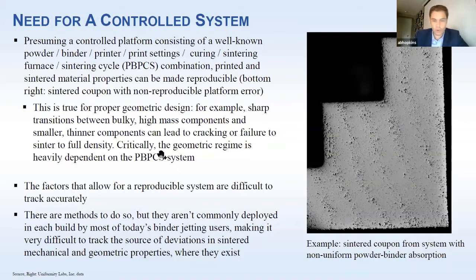All right, great. So once you have a controllable system, you have the problem of geometries again. Is it controllable for all geometries? Or when you sinter, you're going to fracture. So you might see a fracture point at sharp edges in sintering if your part is large enough, even in a controlled system. And it depends on the alloy, it depends on your peak sintering density, it depends on your parameters, highly dependent. So you will get warpage. The warpage is hard to predict. So binder jetting is great. It's cheap. You can get controlled systems, relatively speaking.